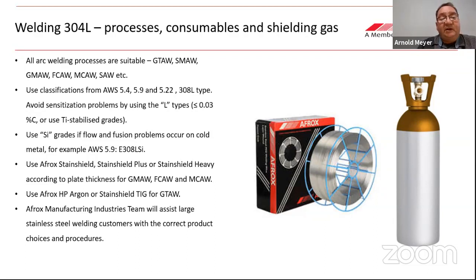Then in terms of shielding gas, Afrox has Stain Shield Plus and Stain Shield Heavy, and that depends on the thickness of the material. The Plus gives a little bit of a warmer arc than the Stain Shield, and the Stain Shield Heavy gives the warmest arc. For TIG welding, use HP argon or Stain Shield TIG, and always purge with HP argon. That's the best purging gas that you can get.